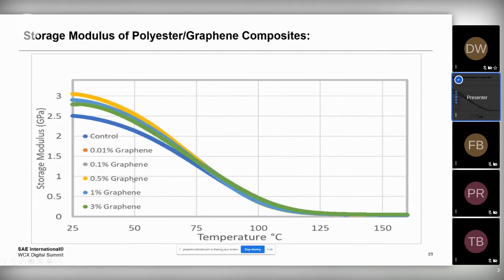And one of the things we see here is with a dynamic mechanical analyzer, we're able to look through a sinusoidal wave over a range of temperature, and we're able to see the impact that graphene is having at very, very low loadings upon the modulus properties of a polyester composite, and that in turn translates fairly significantly in terms of your compressive modulus, so compressive strength. So looking at this here, at 0, your control is right here in terms of the modulus you're getting, starting off at about 2.5 gigapascals storage modulus at 25 Celsius, and you can increase that modulus when you get to 0.1 or 0.5% between 18 and 28% increase in modulus.